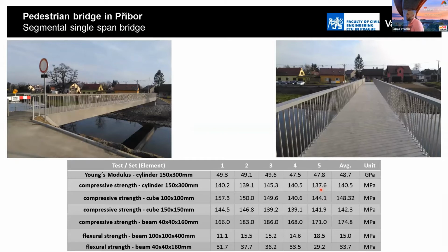Some information about the tests of these elements, about the compression strength, the modulus of elasticity, and also the flexure strength on the beam. About the modulus of elasticity, normally the average value was approximately 48 gigapascal. Again, comparing normal concrete, it is a little bit higher. Compressive strength depends on the shape and the dimensions of the element. For the cylinder, we obtain a compressive strength of approximately 140 megapascal. For a cube with sides of 100 millimeters, the average compressive strength is 148 megapascal.